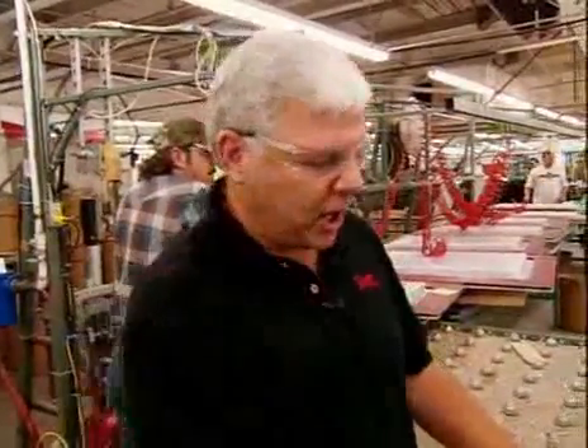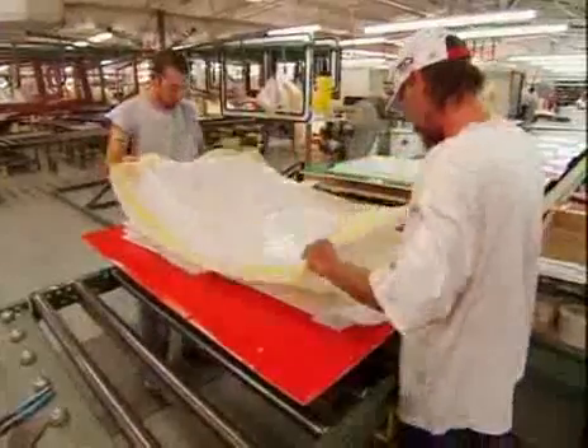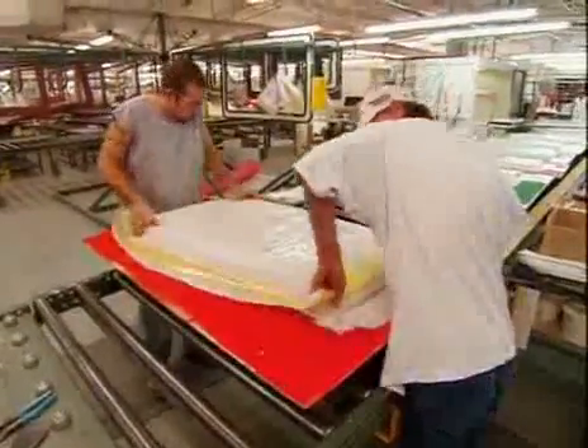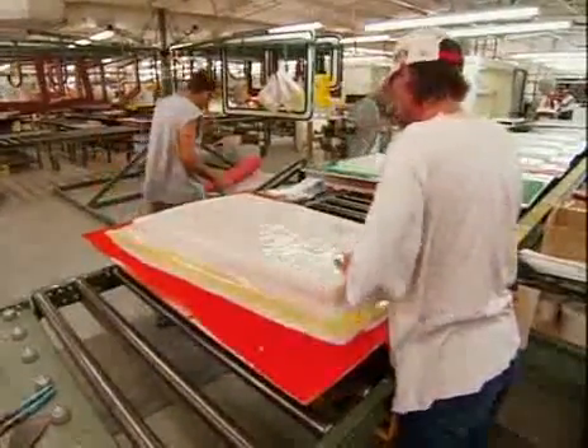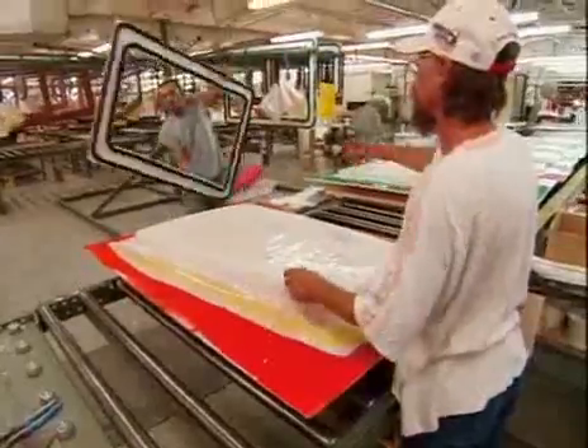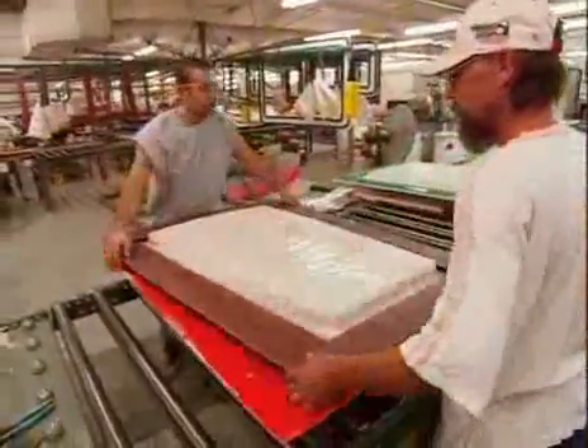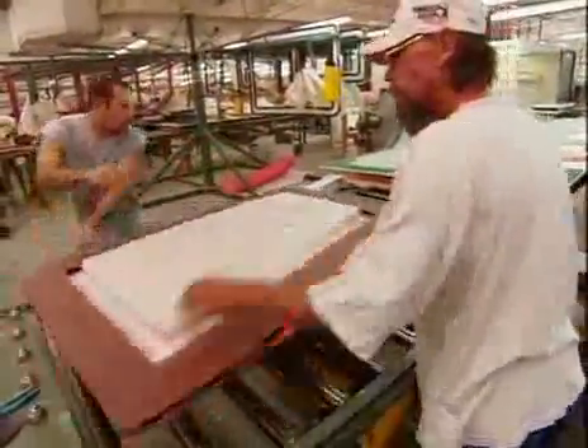One of the important things of using the foam and the fiberglass is because of the thermal barrier qualities that glass has along with the foam core. What we've found, as opposed to a lot of the aluminum lids that are used on competitive products, is we see upwards to a 20% reduction in heat from the ambient temperature outside, for example, to the inside of the live well. Now that's important if you're fishing in a hot summertime and you're trying to keep those live wells as cool as possible.